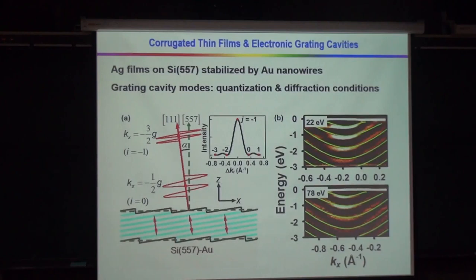Okay, just on a side note, I mentioned the film on a substrate, the interface is really not flat, in the sense that you do have atoms. So films are made of atoms. The surface is also made of atoms. And to prove that this atomic effect is important, there's one trick which you play. That is to start with the substrate cut at an angle. So you just imagine these atomic layers of the substrate. But instead of making this a perfect plane, we cut at an angle.